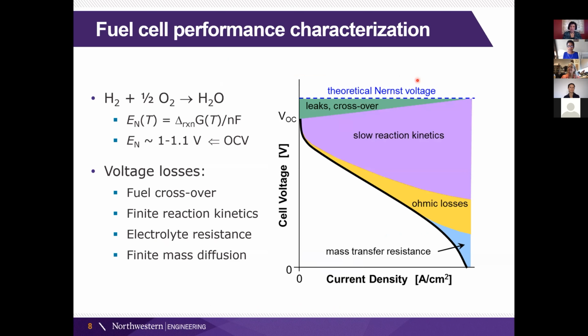The way that we measure fuel cell performance is to look at the voltage as a function of the current that's being drawn from it, and we convert that to current density so that we have a metric that is realistic in terms of comparing device performance. Our open circuit voltage is determined by the Nernst, the Gibbs energy of this overall reaction. We just divide that by the number of electrons and Faraday's constant to get the open circuit potential, or open circuit voltage. And that's typically a little bit over 1 volt for a typical fuel cell.